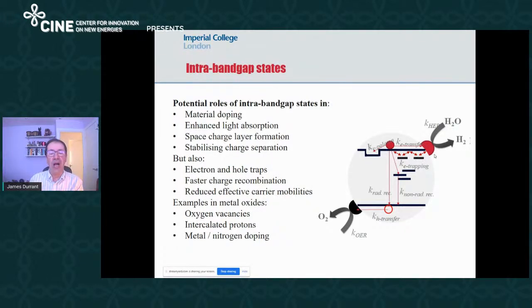Now, the role of states within the band gap in function is quite controversial. Of course, one strategy to make materials better is to dope them. When you dope a material, you introduce states in the band gap. Another strategy to make some materials more light absorbing is, again, to introduce states in the band gap to lower the optical band gap of a material. On the downside, of course, states in the band gap can act as traps and accelerate recombination. And so trying to understand the impact of defect states on device performance is quite challenging and interesting. In particular for oxides, oxygen vacancies are certainly the most prevalent defect in metal oxides.